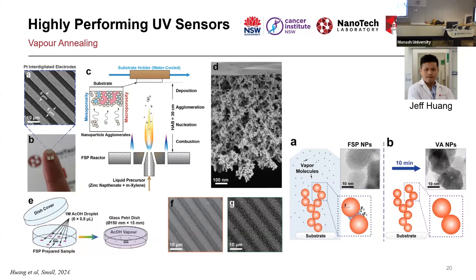And now we remove this sample after 5 minutes, let it dry, 10 minutes, 15 minutes, and 20 minutes. And we see that structure changed again because it's been exposed to a tiny, tiny concentration of acidic vapor. Again, the hypothesis we have is that inside the chamber, we have a lot of droplets. When I remove my sample from the chamber, the droplets are already sitting here, condensated on the gap between 2 particles. And now they've been exposed to atmosphere. They start evaporating. And by evaporation, the same scenario, a Laplace pressure is pulling these 2 particles, and we kind of created a great gap.